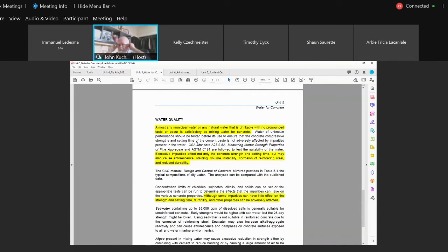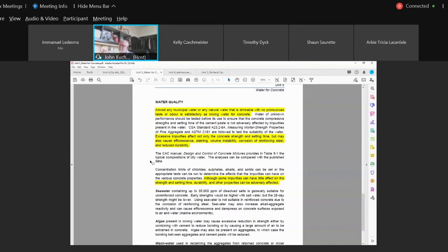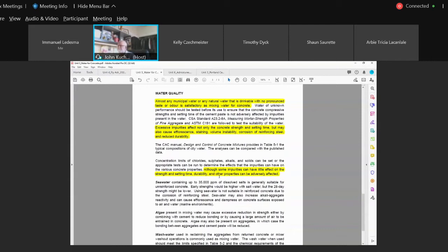It might give you 95%. I can't remember what the limits are, but the cubes have to be a certain percent of the strength of the control cubes, okay? Excessive impurities affect not only concrete, but may also cause efflorescence, staining, volume instability, corrosion of reinforcing steel, and reduced durability, okay? So now we can see why water is important. It may have adverse effect with some of the other ingredients, especially reinforcing steel. It may not react very well with air entrainment, who knows, okay? When in doubt, get it tested.